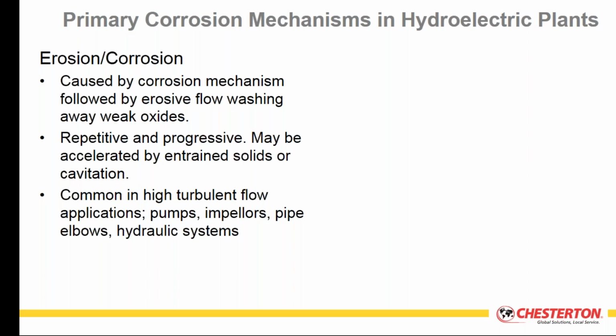So in turbulent flow regions, which are quite common in hydroelectric facilities, that can wash away that weak oxide layer. If there is any type of sand or silt or suspended solids in the flow, you'll now start to introduce abrasive conditions, which will accelerate that erosion rate. Once that passive oxide layer is removed, now you're going to see an accelerated corrosion occurring in that region where the oxides have been removed.